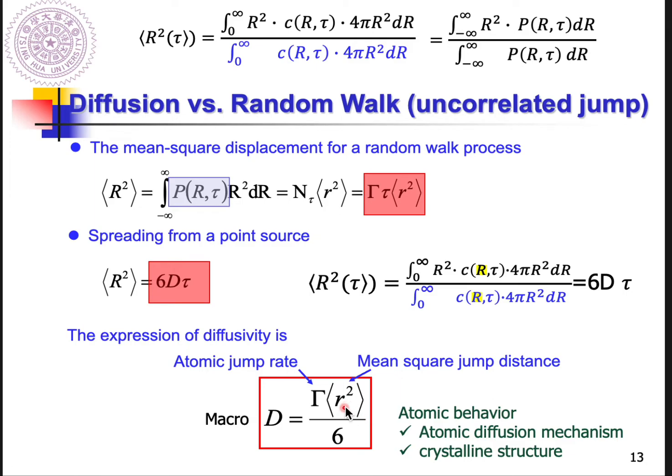If we are talking about the vacancy-mediated diffusion process, that means atoms exchange with surrounding vacancies to diffuse through materials, so the jump distance will be correlated with the lattice constant. But if the diffusion mechanism is the interstitial-mediated diffusion process, the atoms jump through interstitial sites, so that will also vary with crystal structure, right?